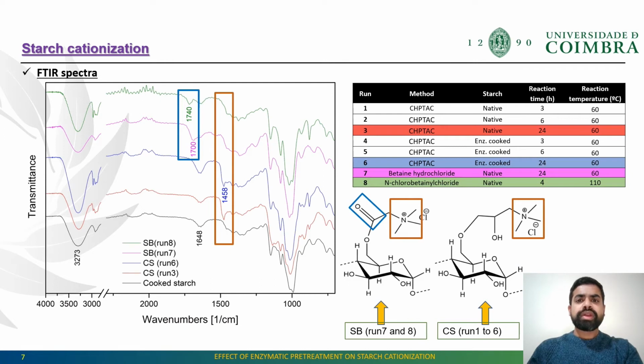As reported in the table, a total of 8 runs were performed covering all three methods, where the first 6 runs are with CHPTAC reagent. Runs 7 and 8 represent the second and third method using betaine hydrochloride. FTIR was performed to analyze the functional groups of cationic starch synthesized using etherification in runs 3 and 6 and esterification in runs 7 and 8, compared with the native starch spectrum.